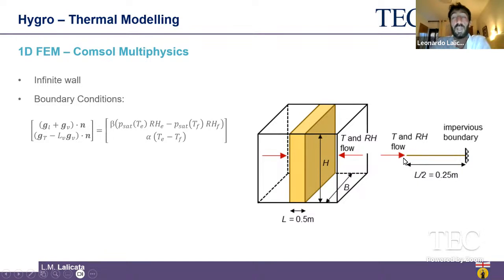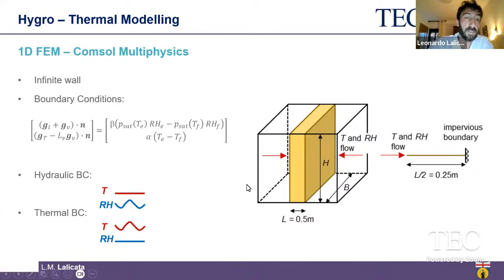On one side, we apply the boundary condition here, and the axis of symmetry of our model is an impervious boundary, obviously. And we played a bit with the perturbations, and we applied a hydraulic perturbation here, in which we kept the temperature constant, and we changed the relative humidity on this boundary here. And obviously, we made the other way around. So we kept the relative humidity constant, and we imposed a daily variation of temperature at the other boundaries.